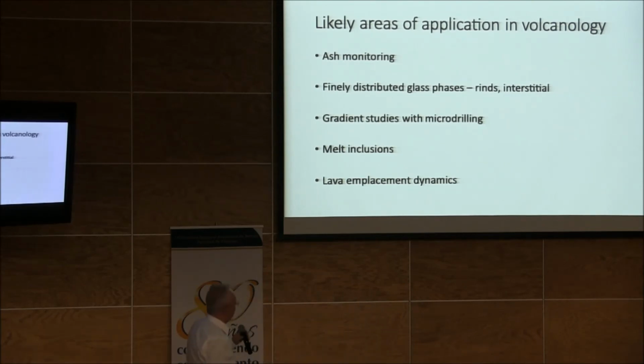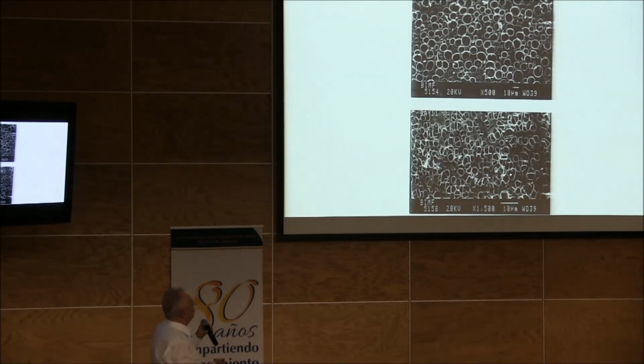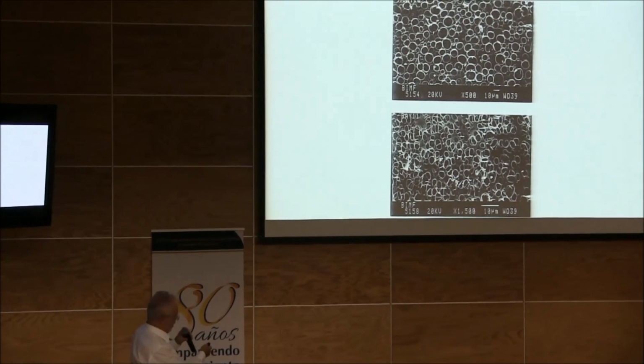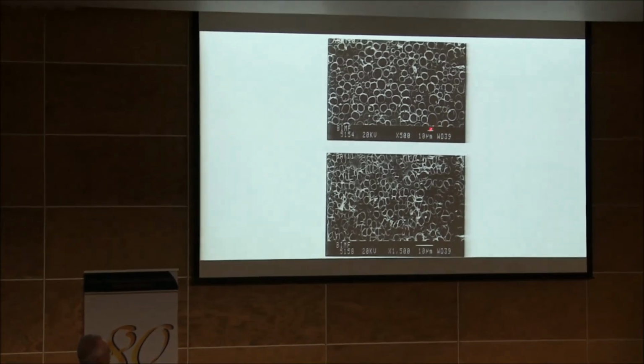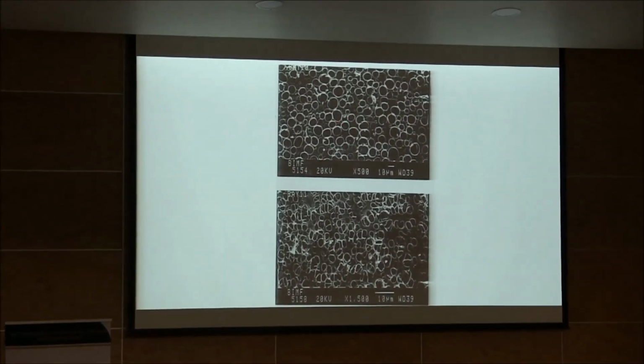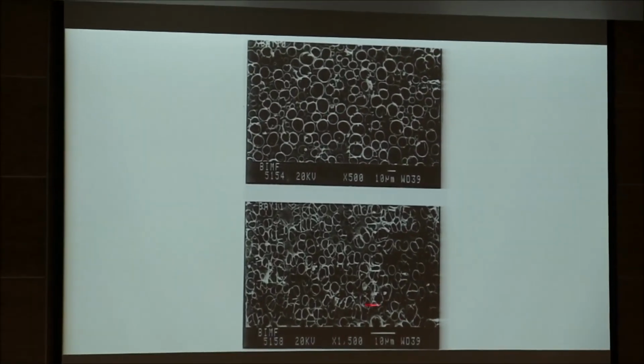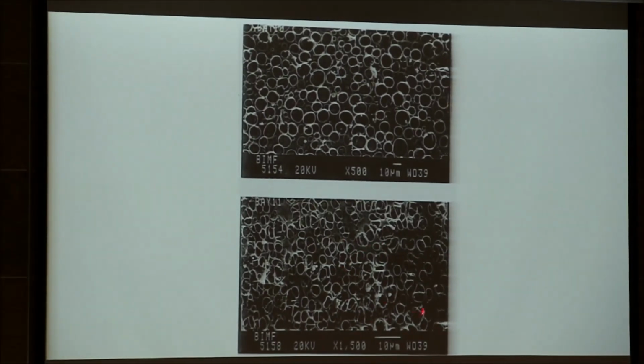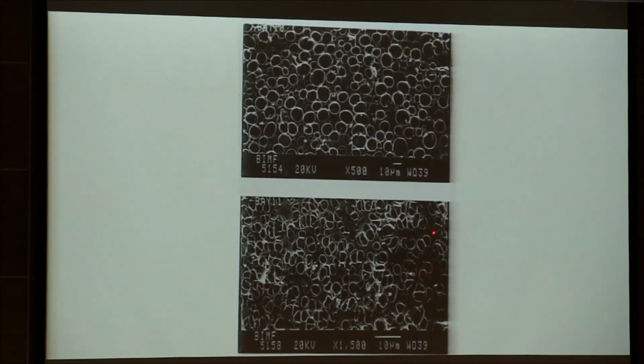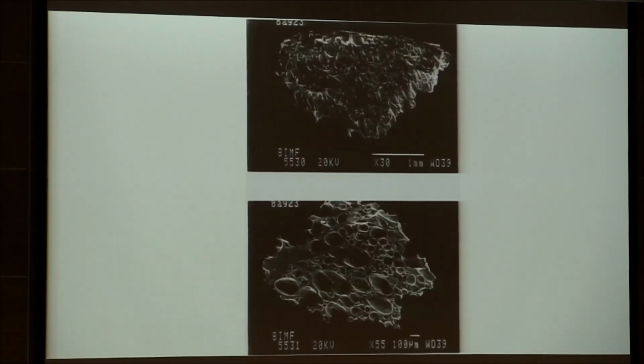And just to give you a finish, I'll give you a picture of the complexity of some of this material. This is the kind of material that we can build in the lab. This is 10 microns. These are the bubbles that we can grow in the laboratory. If you look close enough, you can see very strange features here in these experimental samples, like a pairwise structure of bubbles. You see that? We can also put in gradients in stress and elongate the bubbles, as we commonly see in basalt, and as you'll see if you walk out of the building and walk along some part of the local scenery.